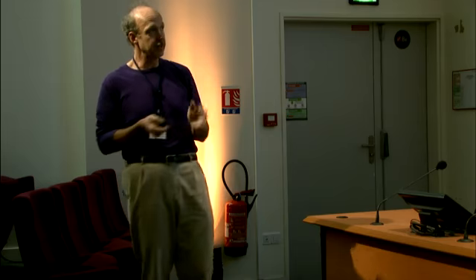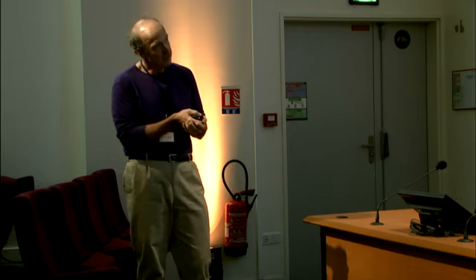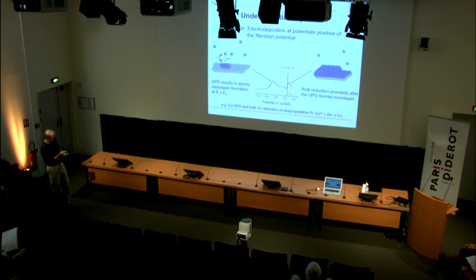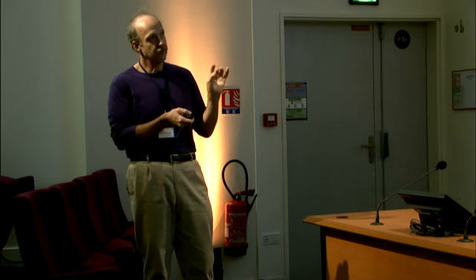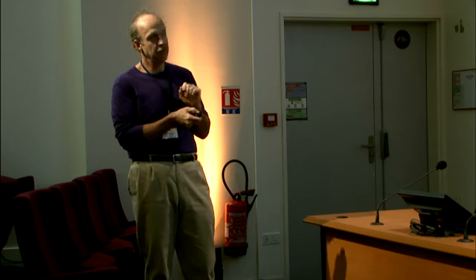the potential negative. And what I see, these are experimental data here, is there's a peak here, and that peak is well positive of the thermodynamic potential for reduction of copper. And what's happening is that the work functions of copper and platinum are such that copper prefers to deposit on platinum more than copper prefers to deposit on copper.